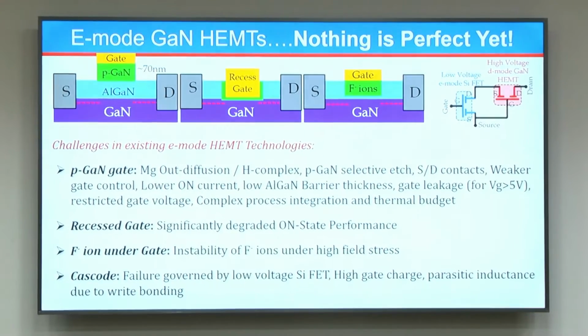But there are a lot of challenges out there. For example, you can have magnesium out diffusion into the barrier layer. You can have hydrogen complexes if you are using a hydrogen based process. You will have to do the pGaN selective etch. The source drain contacts are not as straightforward and not done in the same fashion as you do for the depletion mode devices or the other type of devices. You get a weaker gate control here because of the 70 nanometer thick pGaN sitting over there. You have lower drive currents because you have to deplete the 2DEG. You cannot start with a very high 2DEG concentration.